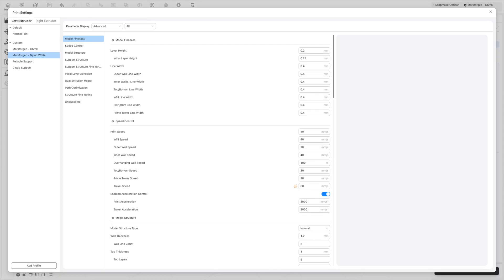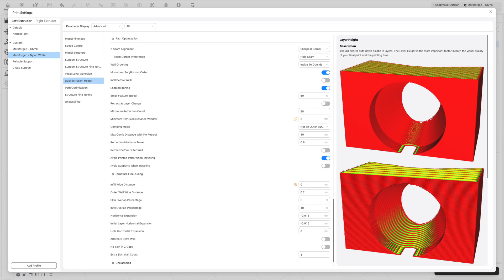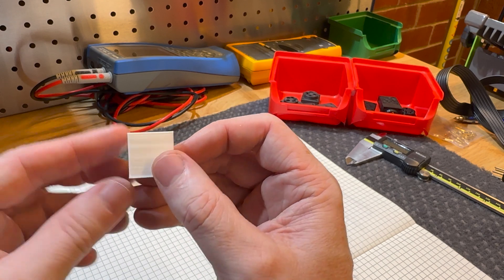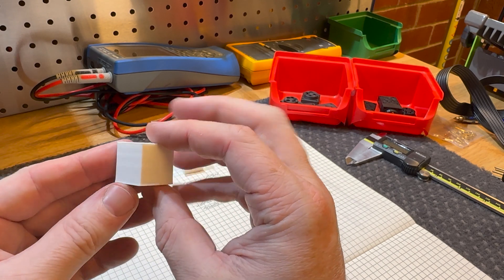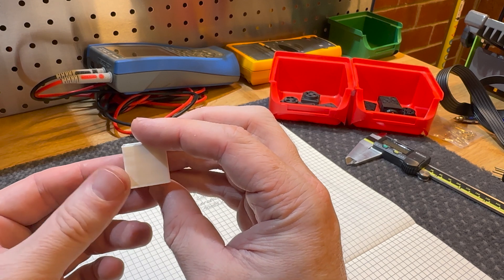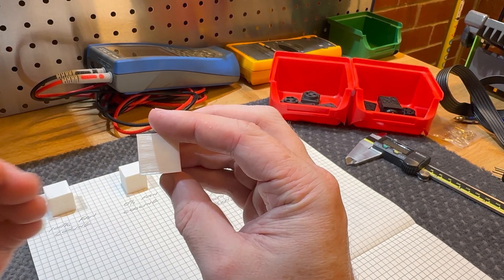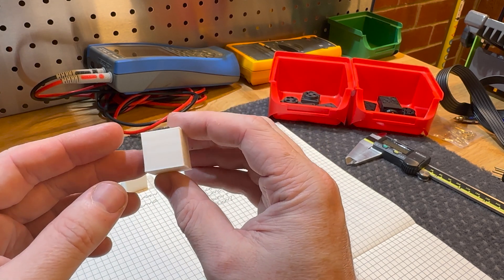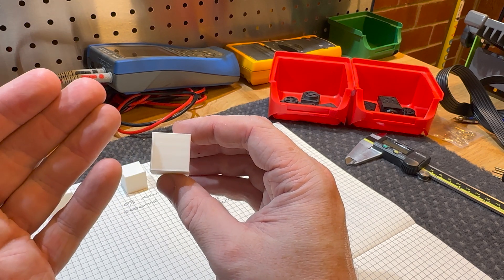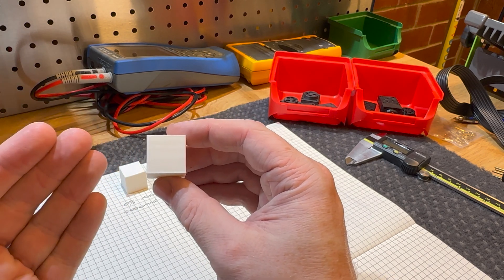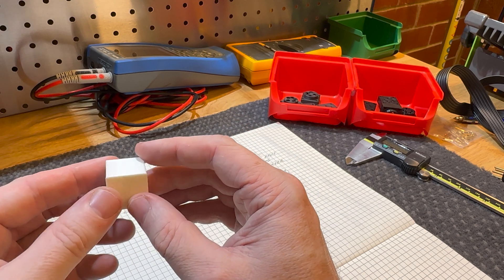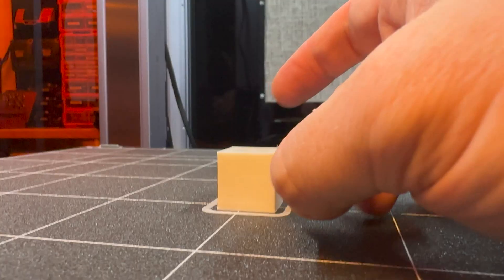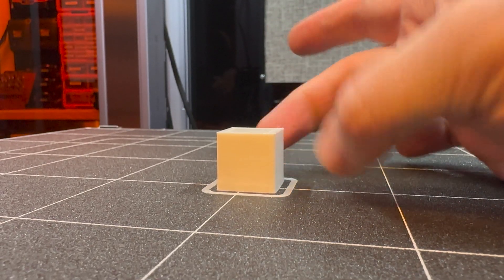And this was overall very good. Quite impressed with it. Overall, it's not perfect—there is still a bit of elephant's foot at the bottom with it sort of rolling outwards, and I need to look into that. But this is not a deal-breaker. It does work, it just needs tweaking. And the layer adhesion was much better using the cooling fan on the first layer for some reason.